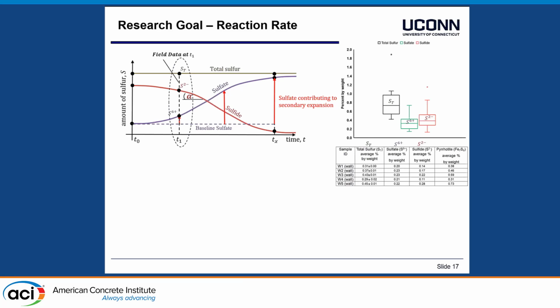But in the field, if we test this, we are at one point in time, for example, this one. And with the test method right now, we can test for total sulfur using the element analyzer. But also if we use WD-XRF, we can distinguish between sulfates and sulfides. So then based on this, we can also calculate the sulfates now contributing to secondary expansion. So this is what homeowners would get in their report: different samples have been tested, obtained from the wall, and then they get the amount of total sulfur, the amount of sulfates and sulfides, and based on the amount of sulfides, with stoichiometry, the amount of pyrrhotite present there.